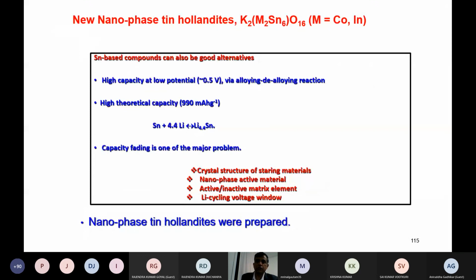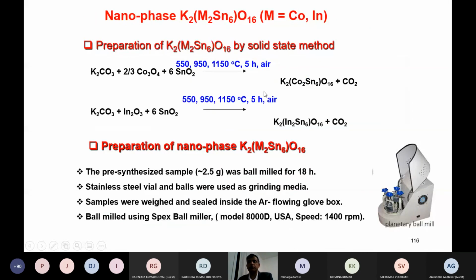Okay. I think one more new compound, again I'm telling you that these are new, reported for the first time, a tin-containing hollandite, although it's a very complex oxide. The beauty of this one is that here a tin-containing alloy element is there, along with cobalt and indium. And again, we tried to prepare the samples. As a first step in research, if it is new, always start with the solid state method. If you want to reduce the particle size, you can use the ball mill. Again, remember these are complex oxides. We need high temperature sintering. We were able to get the sample.